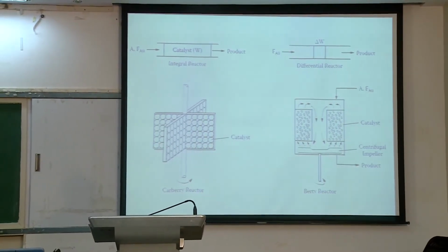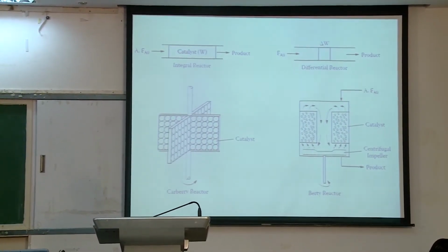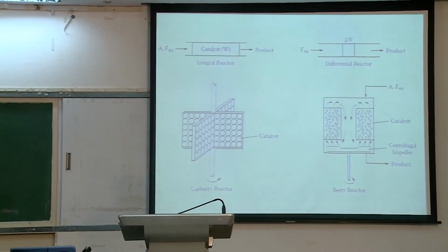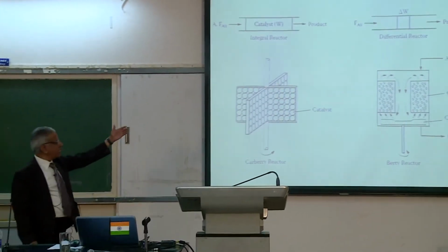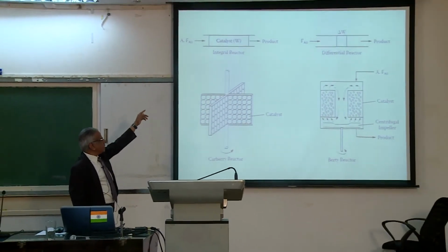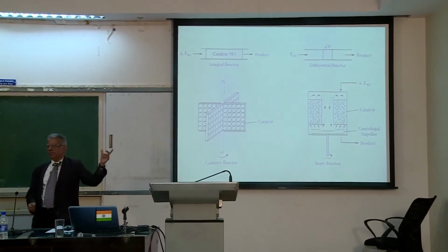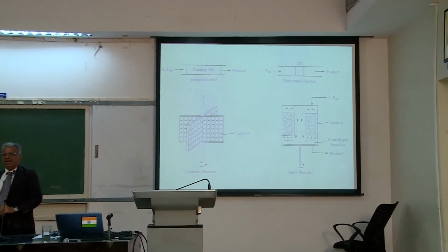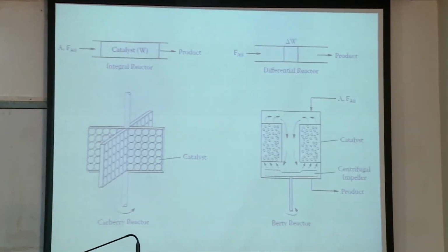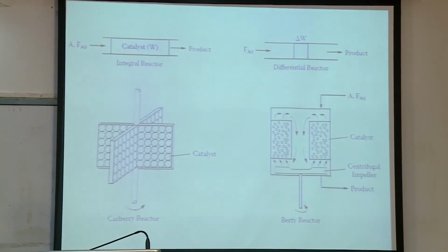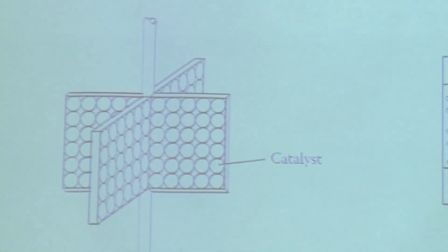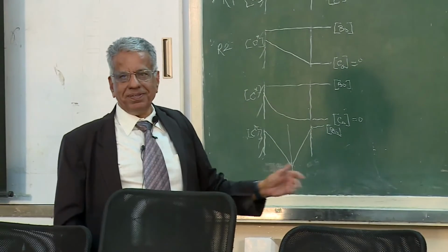Exactly this is the way in which my students in atomic energy are investigating the dissolution of spent fuel, right. It is chopped in such a way that it can fit in this cage nicely, and in a container of 2 liters, you make this a stirrer, put particles, and first of all find out how much time is required for 50% conversion. Hours, several minutes, few minutes, several seconds, few seconds, so that you know the order of whether you are here, here, here or here. Typically it is known.